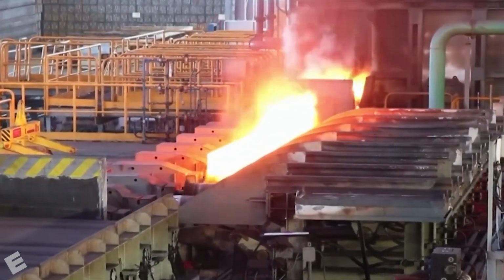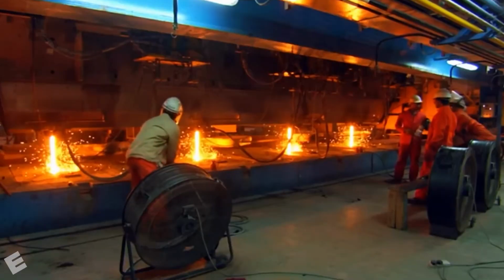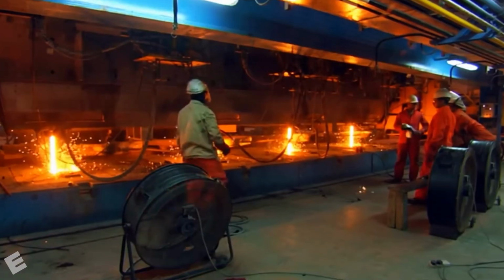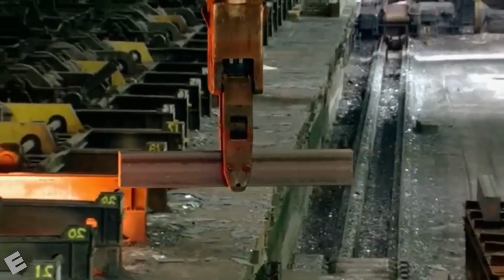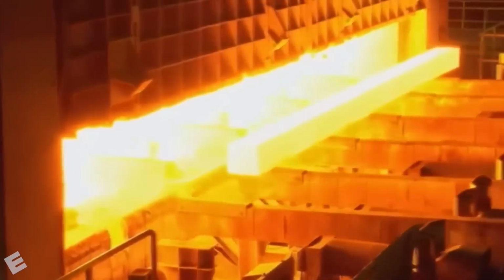The liquid steel is transferred in a large ladle and fed into a continuous casting machine. A ceramic tube shields the flowing metal from air that could contaminate it. Inside a water-cooled mold, it solidifies into a rectangular section called a bloom. Once the strand has solidified sufficiently, cutting torches divide it into blooms roughly 40 feet long. A crane transports them to a reheating furnace. There, the steel is heated evenly to around 2,200 degrees Fahrenheit, making it soft enough to be reshaped without melting.